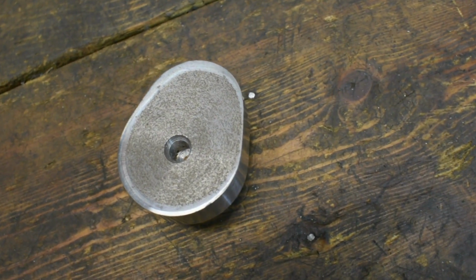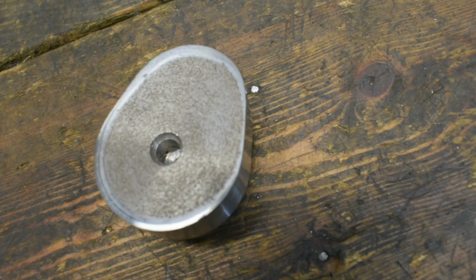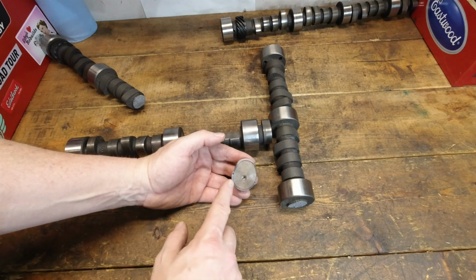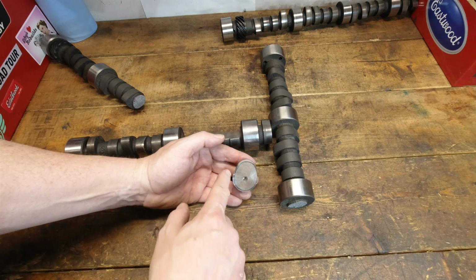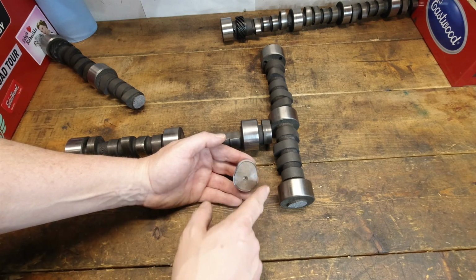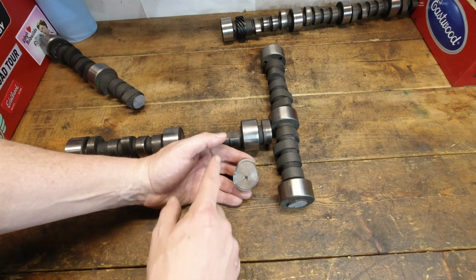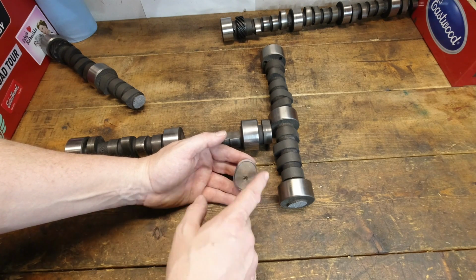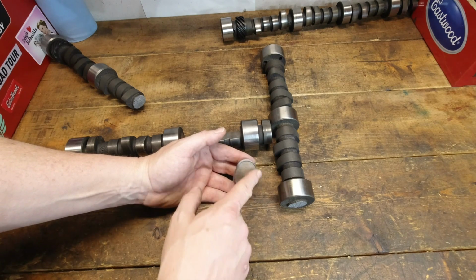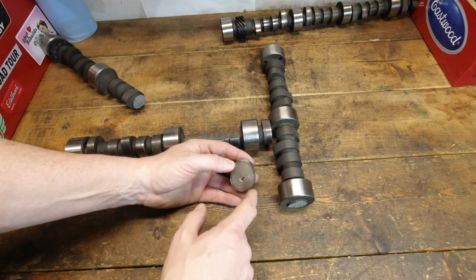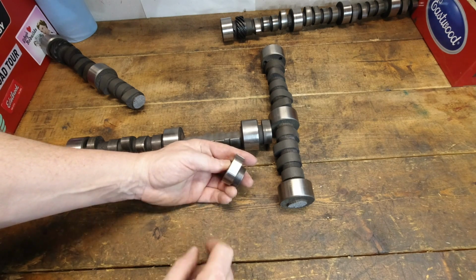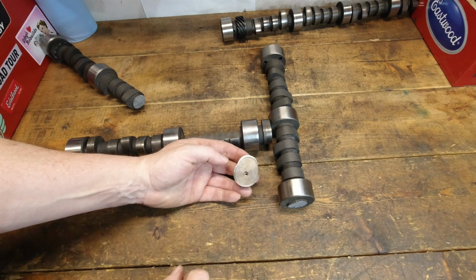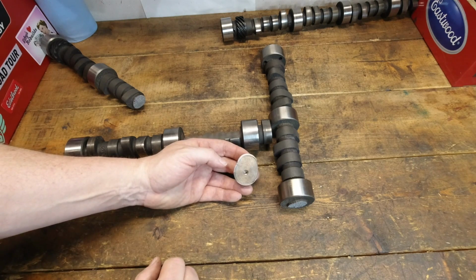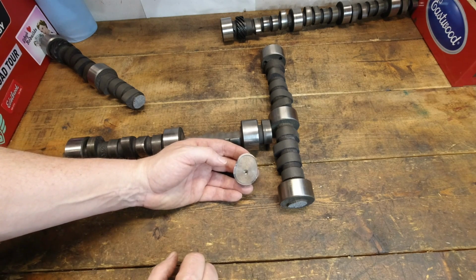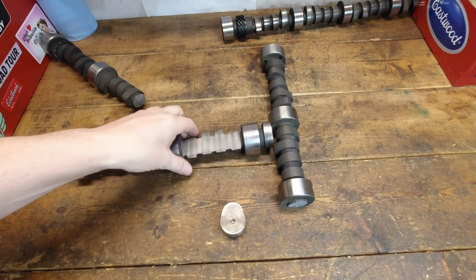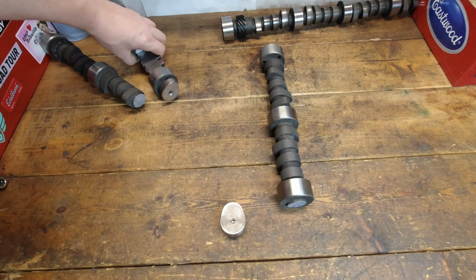But you can run into that situation as well with heat treating, where as long as it's on the ramp side, on the opening side of it and not on the closing, all of the pressure is over the nose on those camshafts or on the ramp here. It's very light on this side, so the chances of that wearing through are thin, but that's a little too thin for my comfort, and I would imagine that camshaft wouldn't pass a quality control test just because the hardness is a little suspect. Now let's take a look at what a billet cam core looks like.